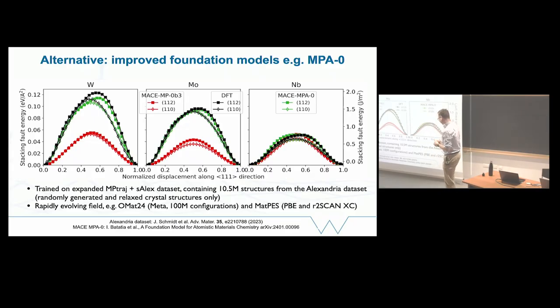So in this case, this is a really nice finding that adding in just these randomly generated relaxed crystals, no defects specifically, but enough different crystal structures, was sufficient to capture the stacking fault energy really well in comparison to the original MP0 model, which didn't.